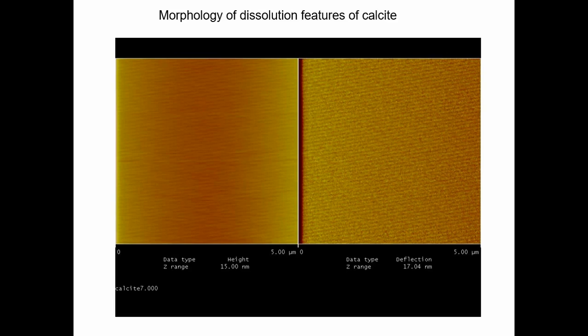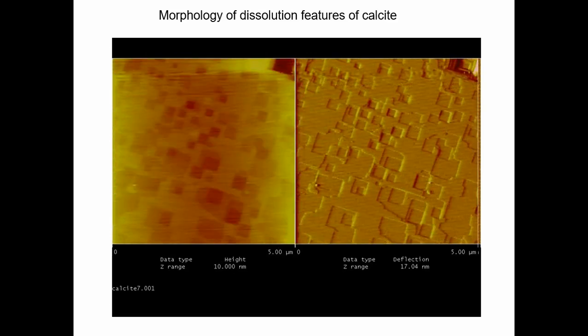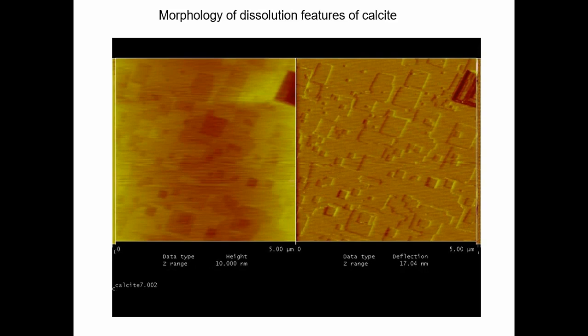Okay, so I'm just going to add water to that surface. There we go. That's after 1 minute, I think. I'm scanning at about a minute a scan for these experiments, and it's a rather large area, 5x5, but as soon as pure water touches the surface, we get dissolution. And you can see there's characteristic etch pits. Look at the top right-hand corner. There's a big deep one there. Etch pits are probably forming at defects anyway, but that is a bigger defect or maybe a threading dislocation.